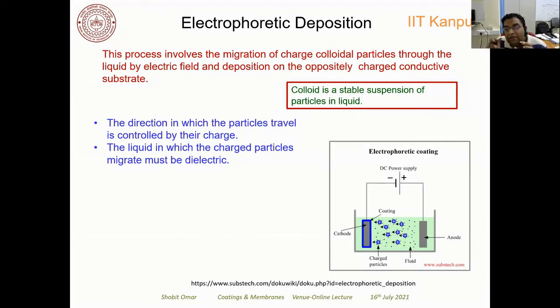What you have is basically a dielectric solution, which is dielectric in nature, and you have charged colloidal particles instead of ions present inside this solution. Now a colloid is a suspension of particles in liquid, right? And these charged particles migrate because of the electric field present in this fluid, and then get deposited on the substrate because of this electric field, right? So the liquid in which the charged particles migrate must be dielectric. It should not be conducting. So this is the difference between electrochemical and electrophoretic deposition.